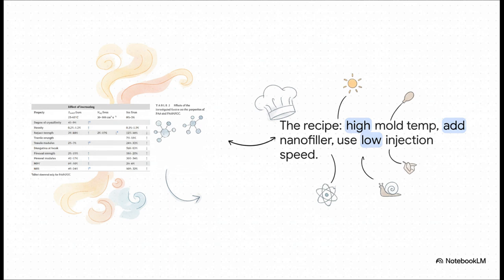First, use a high mold temperature. The arrows show it improves just about everything. That's a no-brainer. Second, add the nanofiller. It gives you a huge boost in stiffness, but you have to accept a small hit to your toughness. And finally, injection speed. The data says keep it low to hang on to every last bit of toughness you can. So the final recipe is clear. A hot mold, add the nanofiller for strength, and use a slow injection speed.